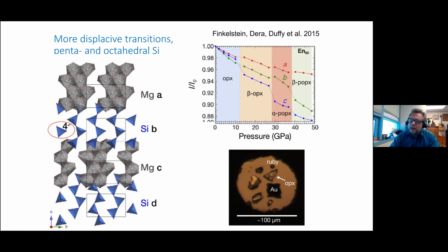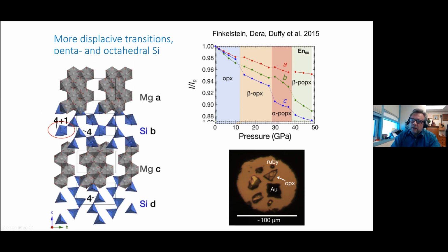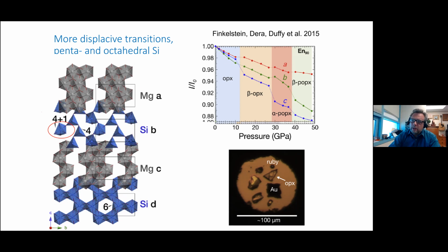Now, what was interesting is when we solved the structure and refined atomic positions, we observed that silicon in enstatite undergoes interesting transformations that involve changes in coordination number. So you can see here the low pressure phase with all silicon being 4 coordinated. As we increase pressure to go to the second high pressure phase, one of these tetrahedra turn, and we get a 4+1 coordination where one of the tetrahedra has a fifth bond that is slightly longer than the first 4. And then as we go to higher pressure, one of the chains transforms completely to 6 coordinated, whereas the other one remains in a mixture of 4 and 4+1. So we can see that pressure in this particular system is an easy tool to adjust coordination number of silicon. All of these phase changes that we found in enstatite are reversible.